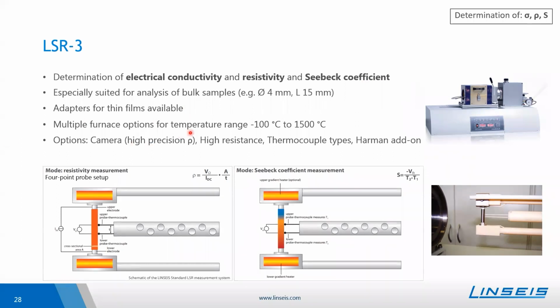There are also different furnace options to cover a broad range of different temperatures. And this instrument setup uses the 4-point probe setup. So we have 2 electrodes where the sample is clamped in between, and we have 2 probes which touch the sample from the side. So here you can see a photo of the real setup. And based on this 4-point probe setup, then the resistivity is determined.